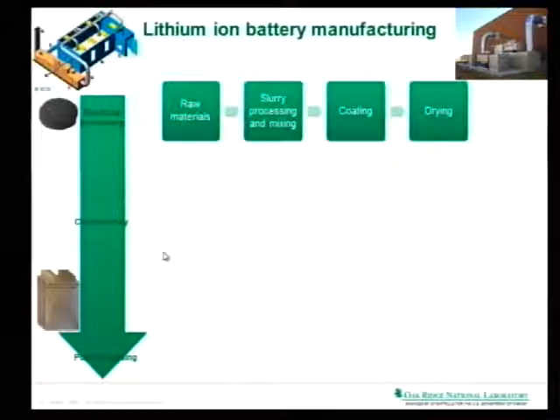So on the electrode processing, it's typically starting out from a powder material. You have active materials, you have binders, you have conductive additives, you throw into the mix together in raw materials, and you process a slurry, which you can then paint onto surfaces, if you will. So you coat those, you dry those, you remove the solvents, and then you have your electrode.